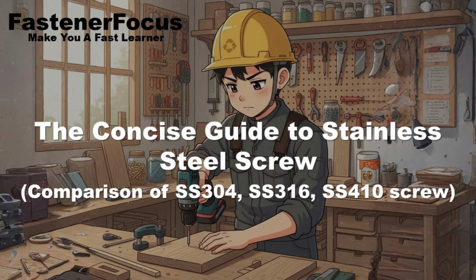It does. Now consider hot dip galvanizing, or HDG. That's a significant upgrade. The fasteners are dipped in molten zinc, creating a much thicker coating, often 1.0 to 4.0 mils thick. This thickness provides superior longevity, suitable for general outdoor construction, especially in contact with chemically active materials like pressure-treated lumber. However, even HDG is sacrificial. In the presence of an electrolyte, the zinc sacrifices its mass to protect the steel. It's a race against time. Once the zinc layer is consumed, the underlying steel begins to rust rapidly. Stainless steel never needs a sacrificial layer because its entire mass is resistant.